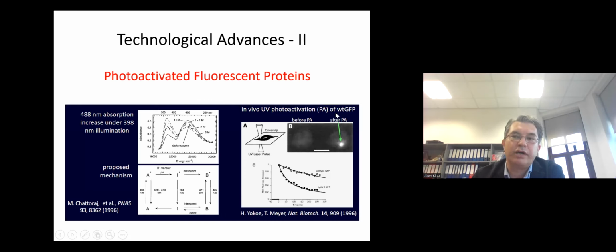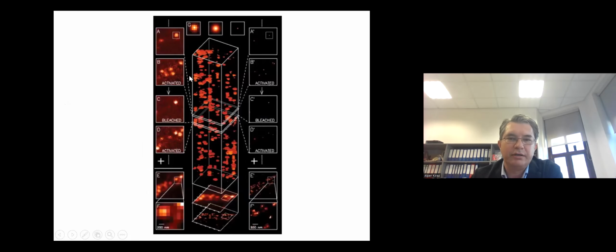And for photo-activation, you need to activate these molecules one by one. What you use is a second laser and a photo-activated dye molecule. So the photo-activated dye molecule in this case can be GFP, and if you give UV light to GFP, you can make it brighter, and stochastically some of these GFPs become brighter, and you can localize them. So this was the technique.